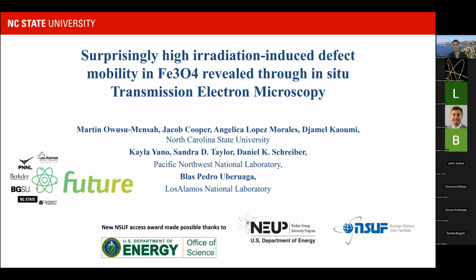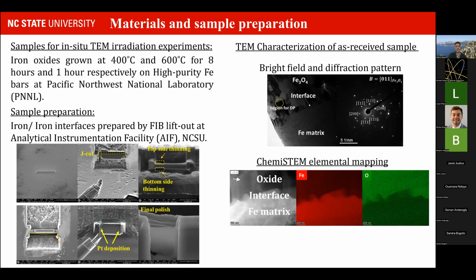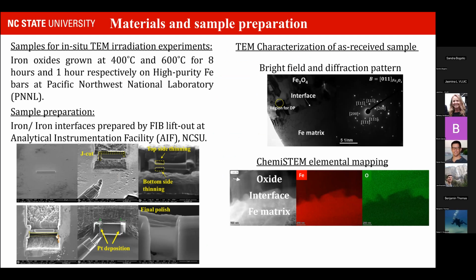More recently, we have been applying this type of study to studying defects in oxides. And this is part of an EFRC that I'm part of, where we're looking at how irradiation affects the corrosion processes. For that matter, we corroded some samples of pure iron, and then processed some TEM lift-out at the interface between the metal and the oxide, and those samples were irradiated.